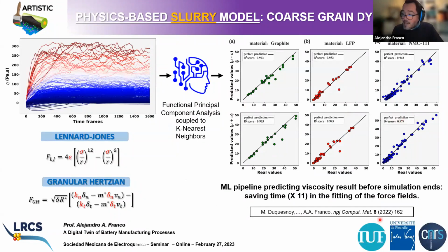We published last year a paper where we report a machine learning pipeline which is able to predict the results of these physics-based simulations in terms of viscosity and density before the physics-based simulation finishes. In such a way, we can forecast the results of the physics-based simulation without the need of running it until the end, knowing that a physics-based simulation like this can be very time-consuming. Thanks to this machine learning model, we can accelerate the optimization of the parameters that we need to put in the force field in order to match correctly the viscosity and the density values from experiments.